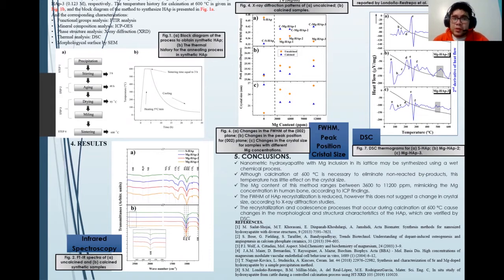In infrared spectroscopy, the spectra confirmed the presence of hydroxyapatite in all uncalcined samples. This can be seen in figure 2A. However, they also had bands of nitrate and carbonate functional groups as reaction byproducts. For this reason, the samples need an annealing process at 600 degrees Celsius. This temperature was enough to remove the additional compounds, as shown in figure 2B. Continues with SEM.